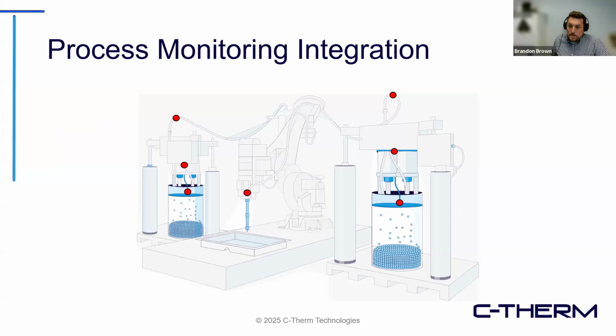Process monitoring integration, right. So with all that background, we can now start to think about integration locations. Here's a bit of a line art rendition of a two-part dispensing machine with all the safety barriers removed. In essence, you have two barrel preparation systems and a dispensing head. On each barrel preparation system, there are three general locations that we're testing: on the follower plate, near the pump, and after the pump along the material transport hose. The final potential location you could monitor the material is right at the dispensing head, right near the mixer. In partnership with bdtronic over the past few years, we've experimented with a lot of these locations. Next slide, please.